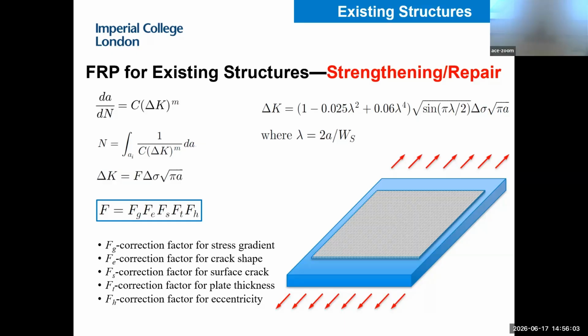So we were inspired by modification factors. Here, for the theoretical stress intensity factor, there is a modification factor. Why do we need it? Because delta sigma times the square root of pi a, that is the delta K for an ideal, infinitely large steel plate, and we need a lot of modifications. We need to modify this delta K considering the finite size geometry of the steel plate, and consider different stress distributions and different shapes of the crack. That's why in common steel design standards, they introduce a lot of modification factors.